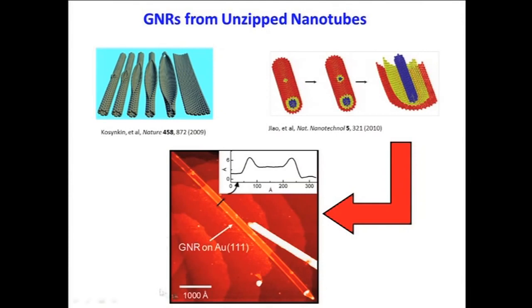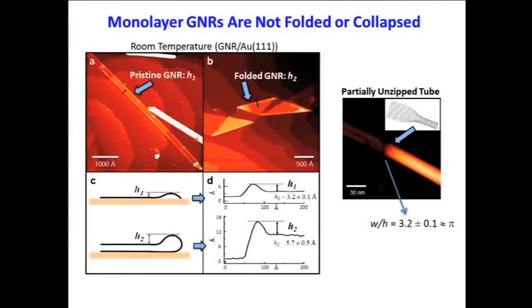And here's a cross-sectional slice, at this little black slice right there. And you can see that near the edges, we see this curvature, which we did not expect. It was kind of an unexpected feature. And that kind of threw us off at first because we thought that maybe we were seeing crushed nanotubes or graphene that was folded under. But we put a lot of effort into looking at different samples, and we actually investigated folded nanoribbons to really see what's happening at this edge. And we determined this edge we see here is actually not folded under. It's not a crushed nanotube, and it's not folded under. We believe very strongly now that what we're seeing is a terminal edge, as I show in this little cartoon, but we just happen to have some curvature right here at the edge.